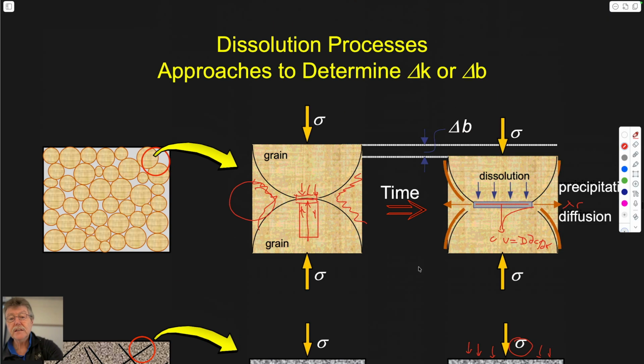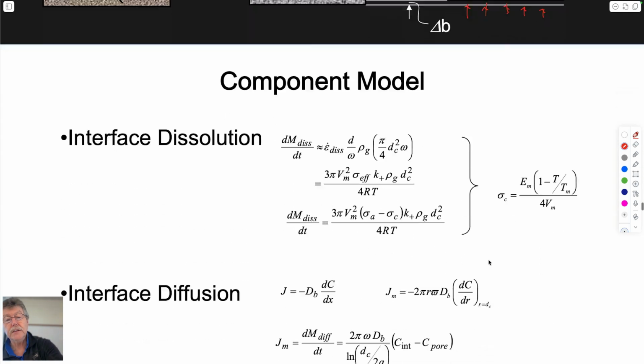So you have a model that looks basically at this behavior, solving a diffusion equation to transport dissolved matter as it's dissolved into the contacting fracture. It goes into the fluid of the pore space, it raises the concentration in the pore, and all of a sudden at that concentration it's supersaturated. It can't hold that saturation in water. It's supersaturated because it's oversaturated by the fact that it's driven by the stress. And since it can't be held in solution, it will precipitate. So not only do you lose porosity by the fact that the grains are growing into each other and the volume in this region here is decreasing, you're also precipitating to actually eat up even more of this volume. So by both agents you lose porosity.